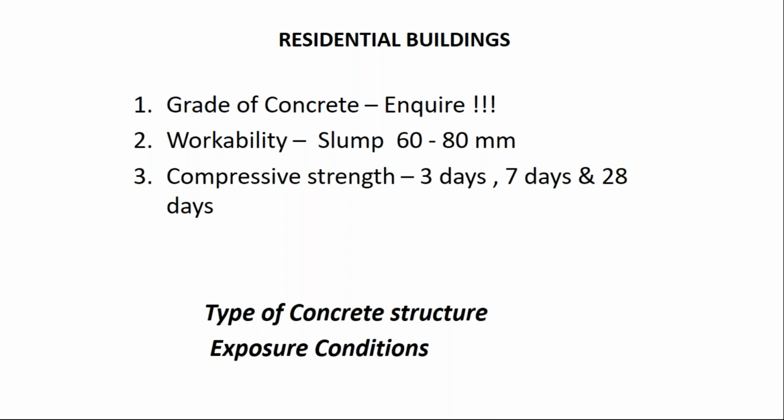Workability, slump is 60 to 80 mm, and compressive strength at 3 days, 7 days, 28 days, most of them measure. But the challenge here is that many of them, as all of us know, go for volumetric batching, which can be quite erroneous at times. And even in residential buildings, we need to look at the exposure conditions mentioned in IS 456. Many a time we will find that the water cement ratio or the cement content that has to be there is not being followed.